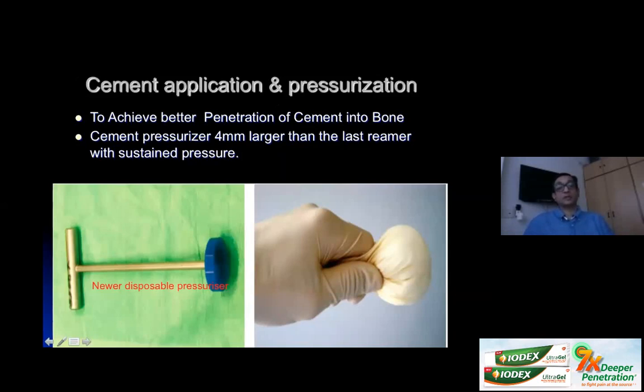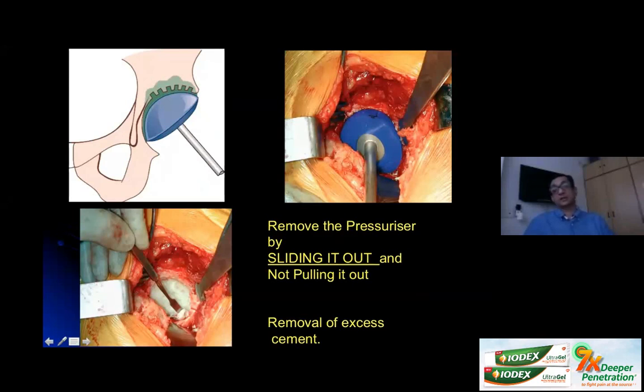Remember, all the cement pressurization should happen with the cement pressurizer, and the cup should not be used like a pressurizer. What the pressurizer helps us achieve is good penetration of the cement into the bone. Initially, I used pressurizers which were handmade with a glove and some gauze pieces, but nowadays we're using these newly available disposable pressurizers. Generally, the pressurizer selected is about 4 millimeters larger than the last reamer that you used, so that it can seal all around the acetabulum and prevent the cement from escaping. Pressurize for about 4 to 5 minutes.